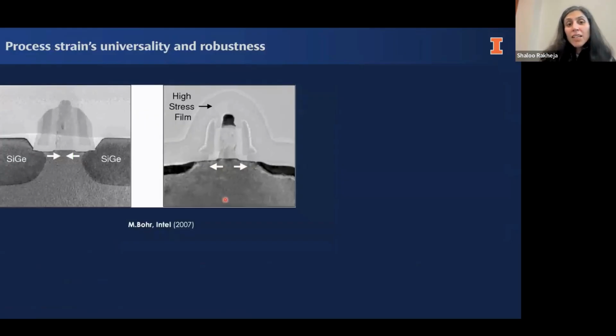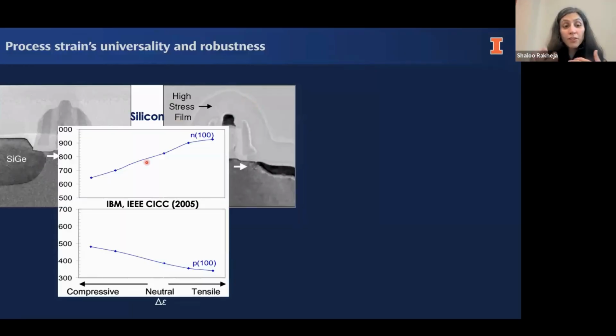Now, I should mention, this is my last slide on strain, and I'll move on to my next topic. Process strain is not a new thing. If you look at your cell phones today, every single transistor inside your cell phone is strained intentionally. And industry has been applying intentional mechanical stress as far back as 2001, in fact, to improve the mobility. They do this by making the source drain embedded with germanium, which applies compressive strain to the P-type material, or they can apply a silicon nitride high-stress film to do a tensile strain. So this isn't new, and people have shown that this can really enhance the mobility of silicon transistors, both N-type and P-type.